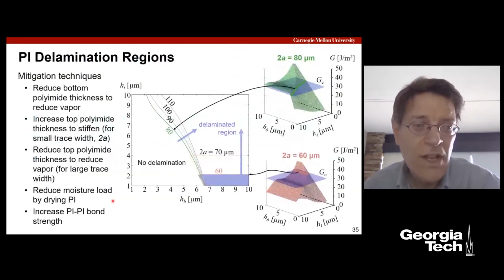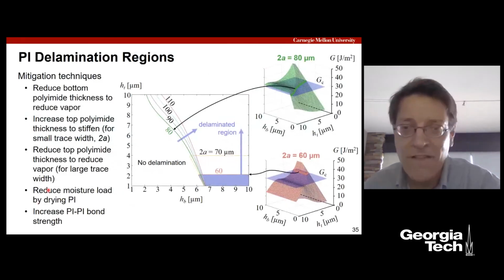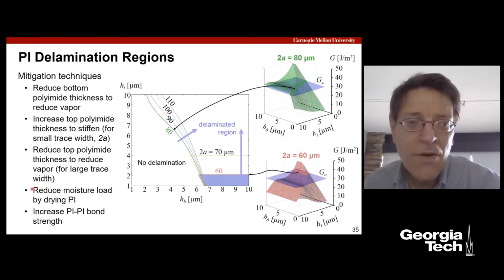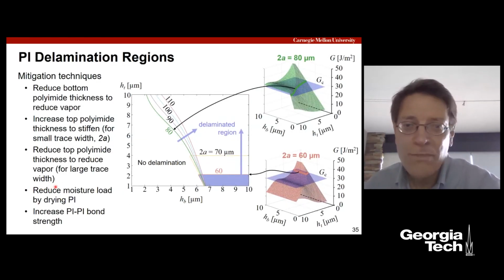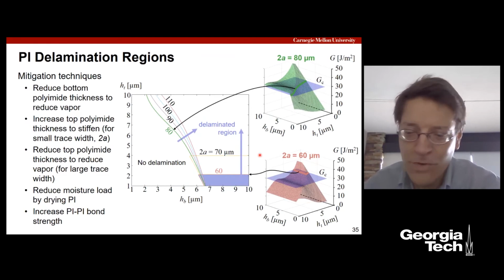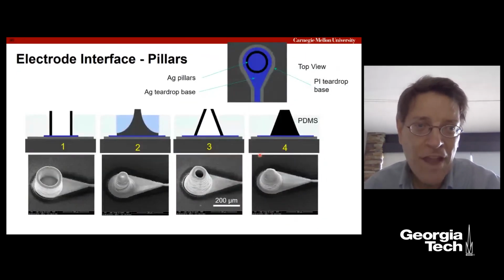Oh, I should mention the other big thing, which is kind of obvious after doing all that: one of the main things to do, before you're going up to 300 degrees C, is dry out the PI, dry out the polyimide. So having this drying step is critical. This just simply underscores that fact.